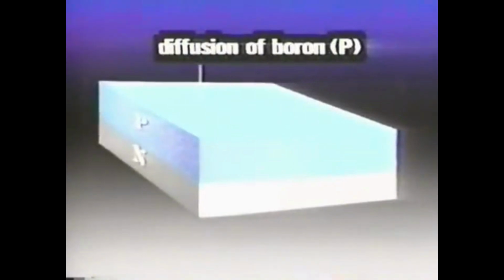Here's the process and structure of the Fairchild Mesa transistor. First, N-type silicon is prepared and placed inside a diffusion furnace and sealed. This liquid is a boron compound used as a p-type impurity. It is mixed with an inert gas and injected into the furnace. The ratio of boron gas forced in is carefully adjusted, because the thickness of the p-type layer that is made on top of the crystal surface varies according to the density of the gas and the heating time. When N-type silicon is heated in the boron gas, a p-type layer forms on the surface.